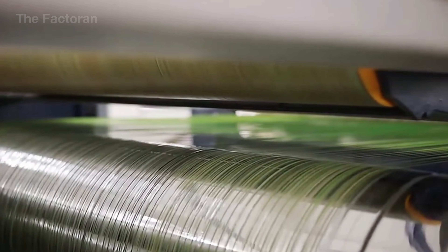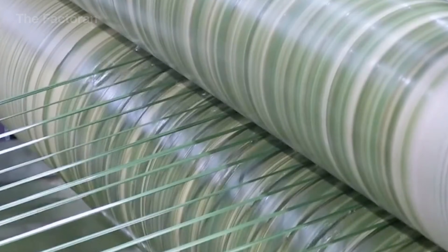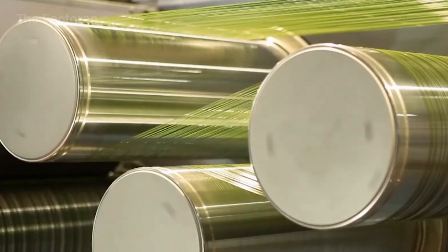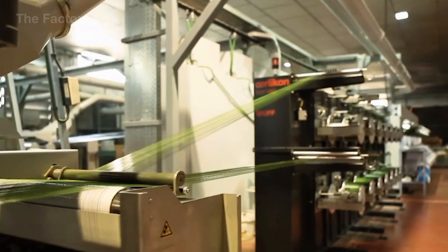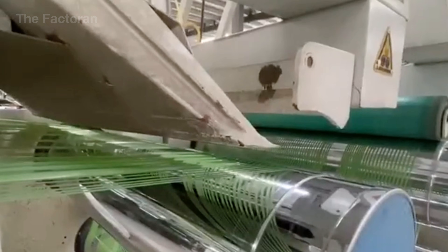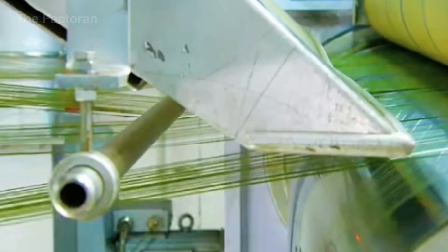Once the outer layer has hardened enough to hold its shape, the downstream take-up system increases roller speed, putting the fibers under constant tension. This is the critical moment — the tangled polymer chains inside begin to straighten along the pulling direction, bonding more tightly and forming a much more ordered structure. The greater the stretch ratio, the higher the tensile strength and elasticity, and the better the fiber stands upright once tufted into the turf backing. By the time the strands exit the draw unit, they are a reinforced fiber built for abrasion resistance and long-term durability — strong enough to survive years of sunlight, rain, cleats, and thousands of matches.